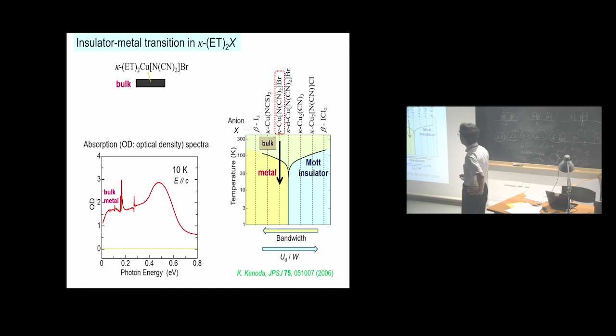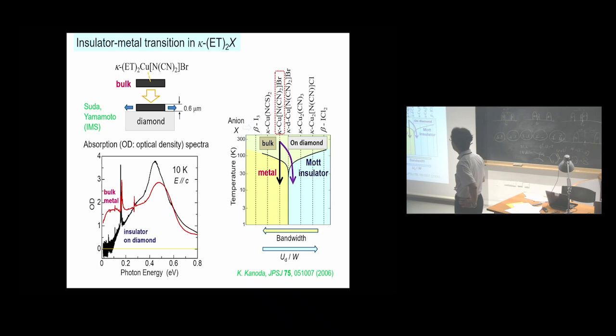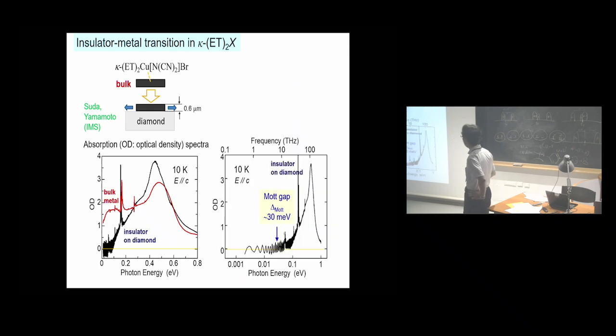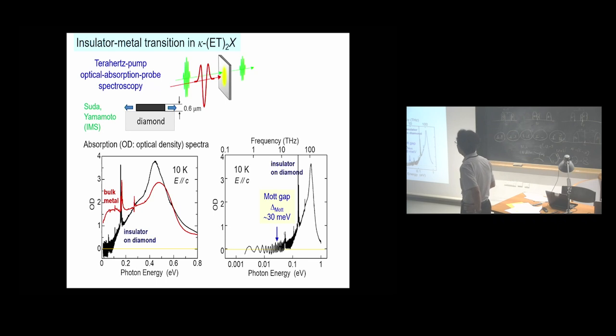A bulk crystal of this compound is a metal at low temperatures. In the absorption spectrum, no gap is observed at 10 K. On the other hand, a thin single crystal on a diamond substrate becomes a Mott insulator at low temperatures because of the negative pressure from the diamond substrate. So, in the absorption spectrum, a clear Mott gap is observed at 30 meV at 10 K. So we perform the terahertz pump optical probe spectroscopy on this sample.